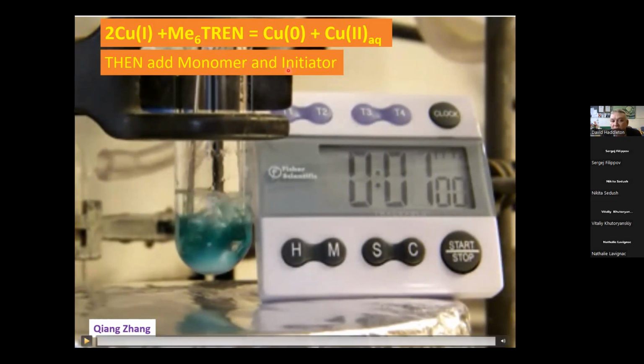and the initiator. If you have the monomer and the initiator present during that 1 minute, then you get 2 different processes. You get ATRP, and you get the mechanism that we're following in water, which is not ATRP. So you would get 2 different polymer distributions and pretty much a mess, really. But if you're prepared to wait a minute, and then add your monomer and your initiator at this particular moment in time, the results in the dispersity and the control are quite spectacular, really. So don't think you cannot do living radical polymerization with copper in water. It's the best solvent, in my opinion, there is.